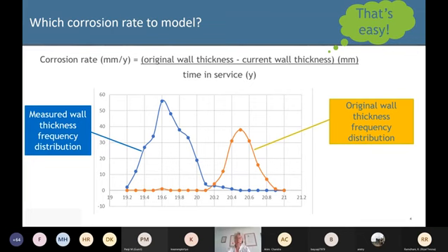So what is the actual original wall thickness? It looks like it should be 20.5, but I can tell you that the actual specified wall thickness in this case was 20.6. Well, more than 80% of the data falls below the specified wall thickness here. And if we look at the blue curve, it is about 300 data points measured circumferentially around a pipe that has been corroding for about 3 years.